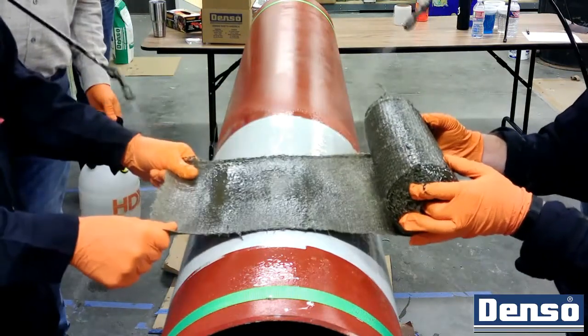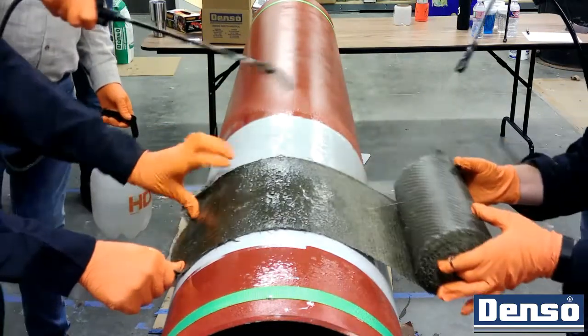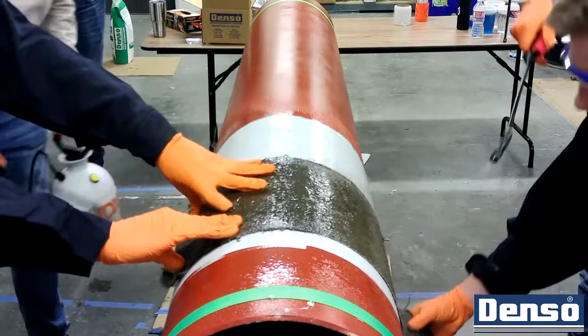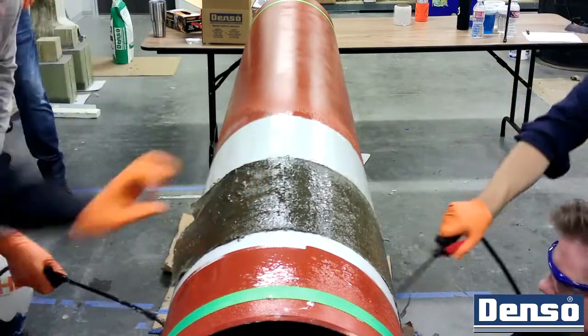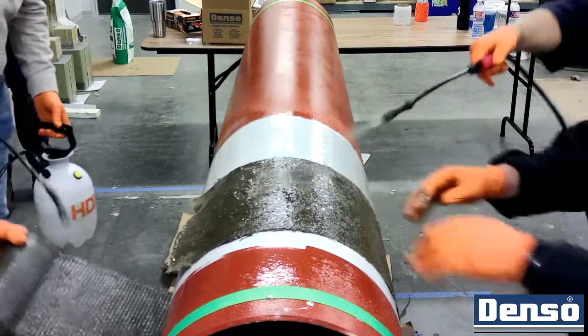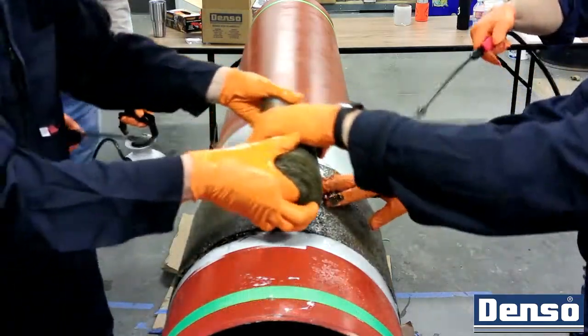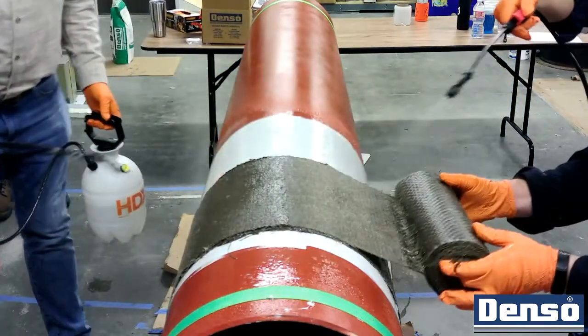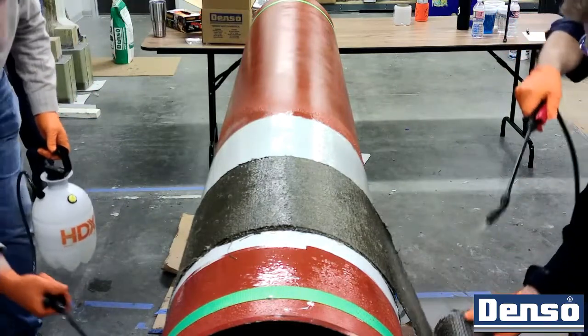Wrap the material circumferentially to begin, ensuring that the leading edge has a minimum of 2 layers. Then, proceed along the length of the pipe, wrapping with a minimum of 50% overlap. Ensure the wrap is completely saturated as it is being applied.